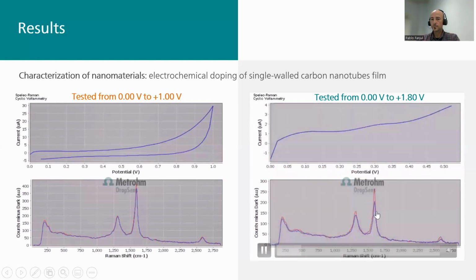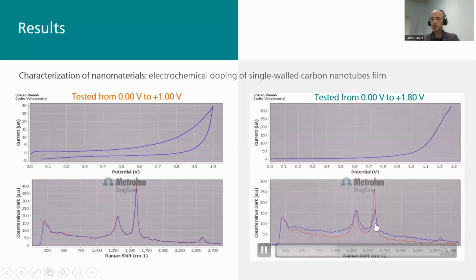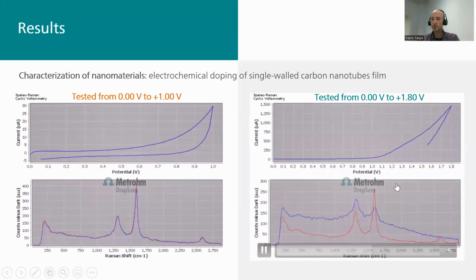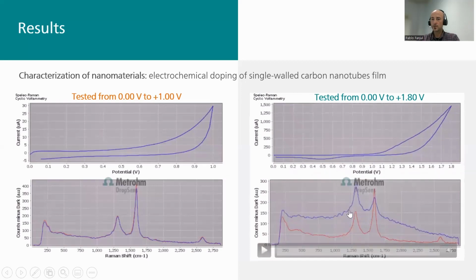In this case, we are oxidizing the electrode, but now at very high potentials, we are generating some defects that cannot be recovered later in the backward scan. So here, now the ratio between the intensity of the D band and the G band is much higher. So we have generated a lot of defects in the structure that are not recovered. So that's not anymore a reversible process. So we are able to understand where are our electrochemical limits, our potential limits to have a structure that can be recovered or completely lost.